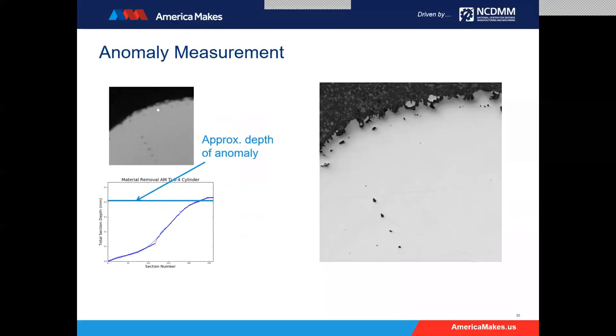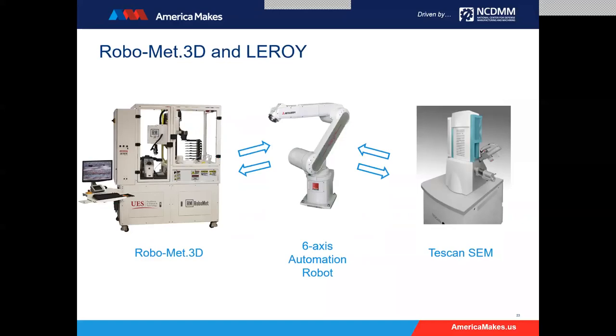We ramped up to the five-micron slice thickness to try to get to this high-density inclusion. We could track our position in the serial sectioning experiment compared to CT because of all the stripe boundaries acting as internal markers. We slowed back down to about one micron as we got close to the inclusion. The top-left shows the CT scan where you can see the bright spot. On the right is the optical image — we somewhat expected to see a dense particle since that's how it looked in the CT, but optically, it didn't really show anything.